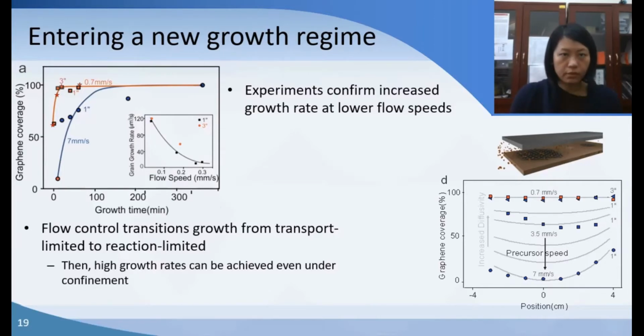And so now that we understand that, we just need to control the flow rate to be really, really slow, so we try to use ultra slow flow rate. And actually by using ultra slow flow rate, it also means we have to flow really, really little carbon radical, which is not so intuitive to us before, because before we always thought that the more carbon we put in, the more the graphene it will be grown. The more precursor you put in, the more it will be grown. But in our case, because flow rate is a dominating factor, the less carbon you put in, the more you actually grow. So that's what we're seeing here. And so with 10 times less carbon that is put in, we can grow like 100 times faster.